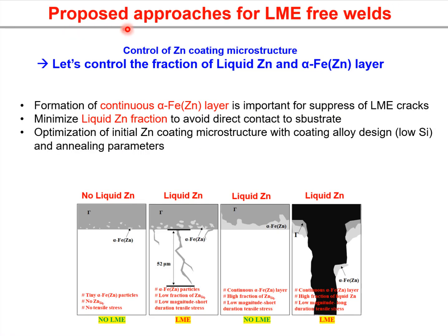First, proposed approaches for LME-free welds: control the zinc coating microstructure. Let's control the fraction of liquid zinc and alpha Fe-zinc layer. Formation of a continuous alpha Fe-zinc layer is important for the suppression of LME cracks. Minimize the liquid zinc fraction to avoid direct contact to the substrate. Optimize the initial zinc coating microstructure with coating alloy design, such as low silicon, and annealing parameters.